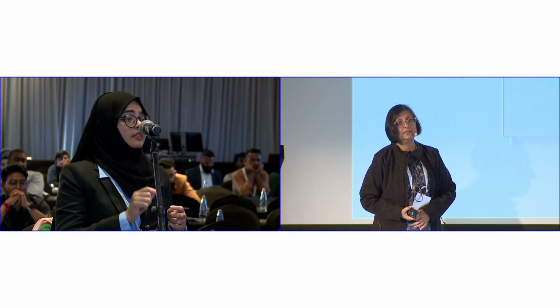Hello, ma'am. As I understand, you are trying to build hybrid perovskites using organic-inorganic components. So I was wondering if you have explored polymers in terms of molecular weights, that is, what type of polymer and how much molecular weight can fit in the vicinity of your perovskite? So that is what I have shown as a tolerance factor, where the size of the organic molecule enters. You are very right that the perovskite structure depends on the cavity. What size can fit in that cavity is given by the tolerance factor. So that was calculated. Does it depend on the molecular weight of the polymer as well? I don't think it's more than the size. Everything is with the size. So the size of the chain, as well as the organic molecule you are putting in the cavity.